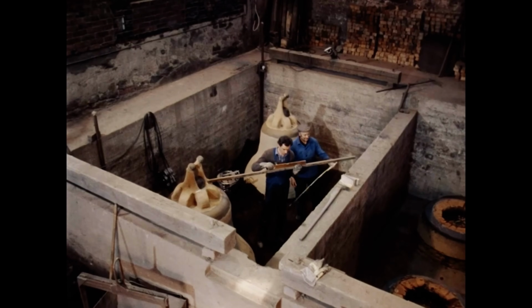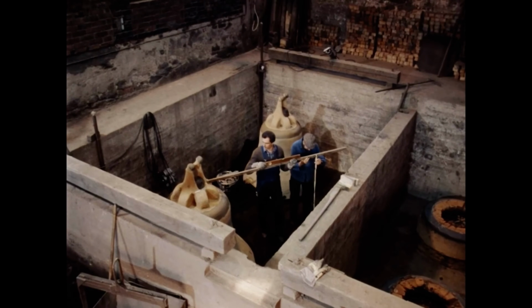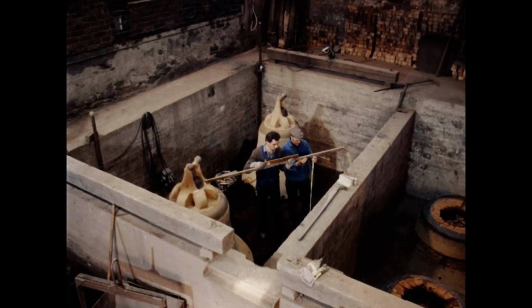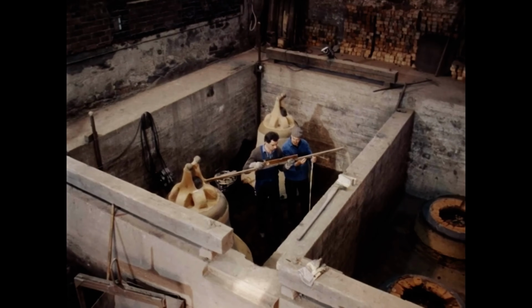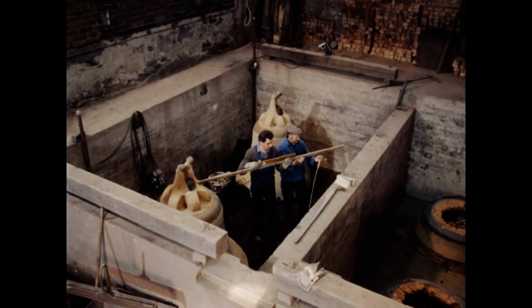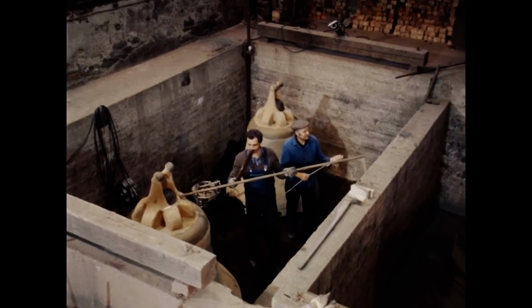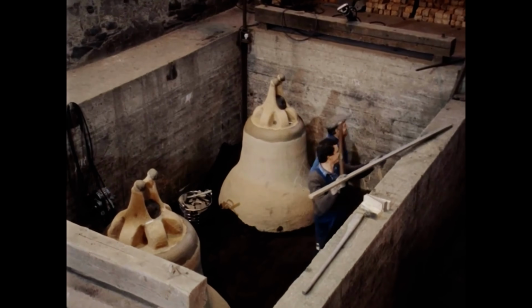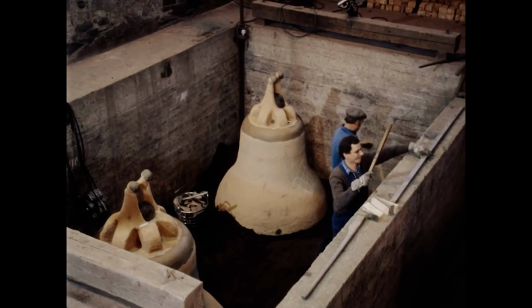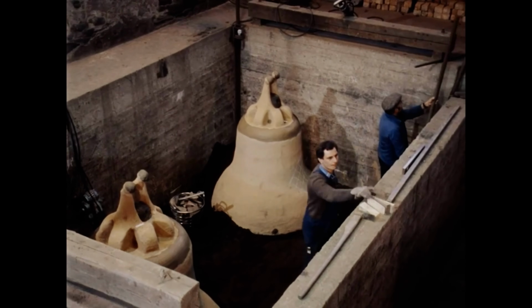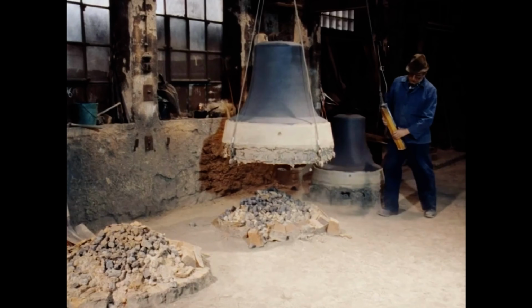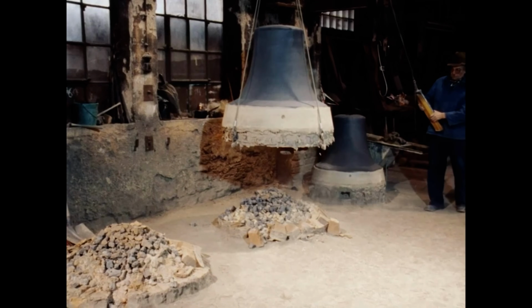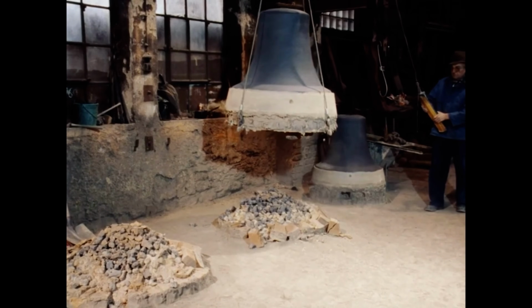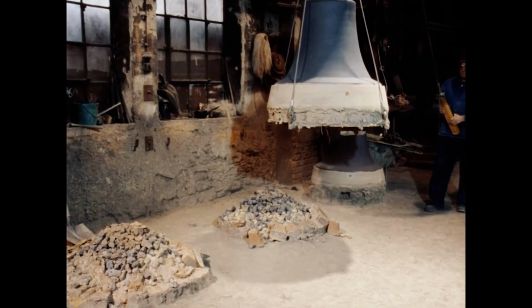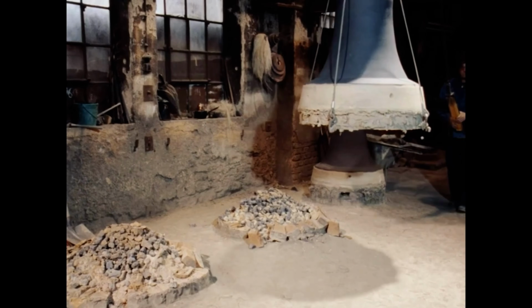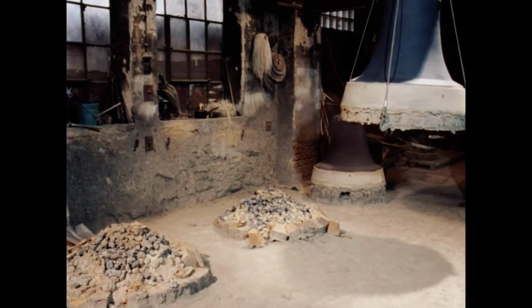Assembling and burying the molds. Of the 5-part chime, the 2 largest bells are cast stationary in the pit. The molders must precisely measure the location of the remaining molds in the open spaces. Large molds don't like to be moved to avoid damage. The 3 smaller bell molds, on the other hand, were made on the floor of the foundry and are assembled in the pit.